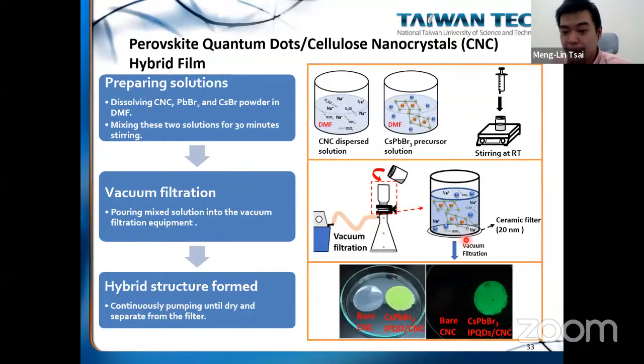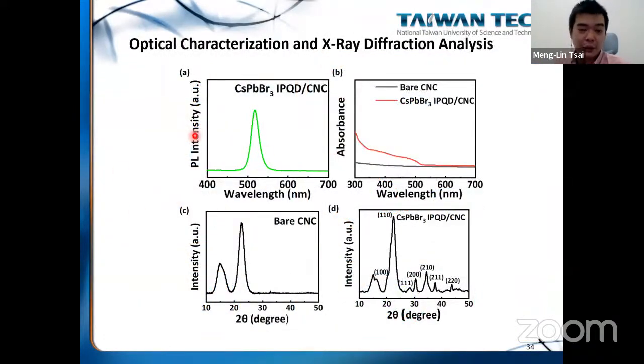Okay, we use a ceramic filter of like 20 nanometer size to successfully synthesize this hybrid film. Okay, and we evaluate the optical properties. Okay, we can see that for this bromide perovskite quantum dot, the emission wavelength is about 530, and we evaluate the absorbance, and we do the XRD to further confirm that the perovskite quantum dot form within the cellulose nanocrystals.